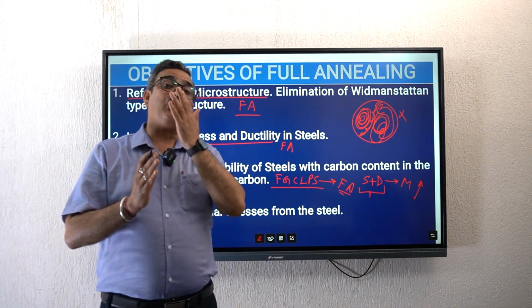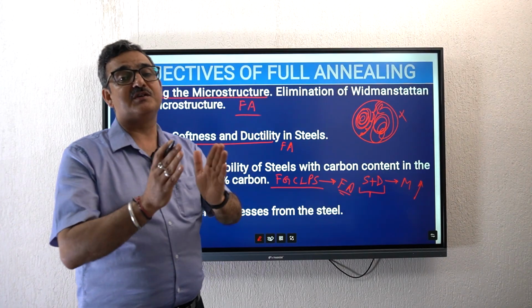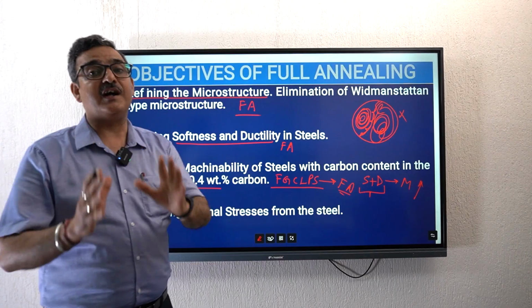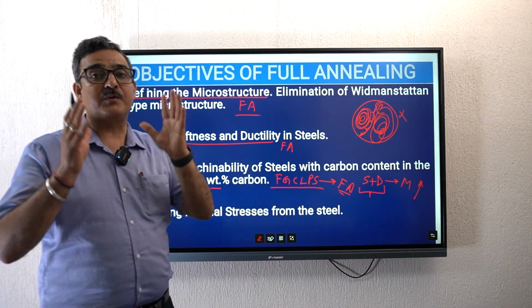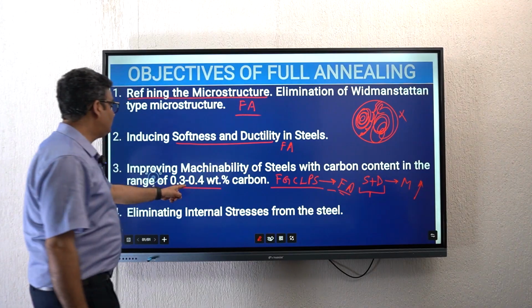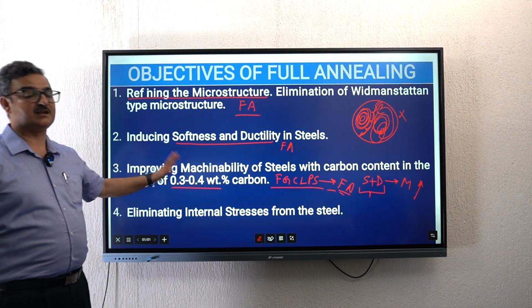0.3 टू 0.4% वाली जो मीडियम कार्बन स्टील्स हैं, इनकी मशीनेबिलिटी कब एक्सीलेंट होगी? जब इनमें फाइन ग्रेन्ड कोर्स लेमुलर परलिटिक स्ट्रक्चर होगा. जो कौन देता है? फुल अनीलिंग ट्रीटमेंट. सो गिव फुल अनीलिंग टू दी स्टील्स टू मेक देयर मशीनेबिलिटी एक्सीलेंट.